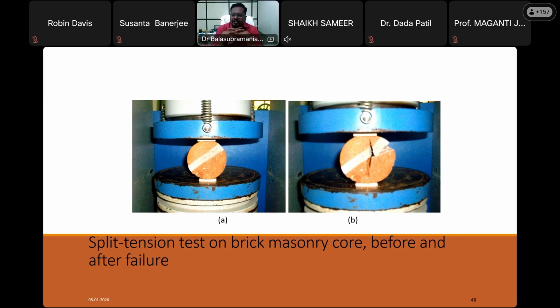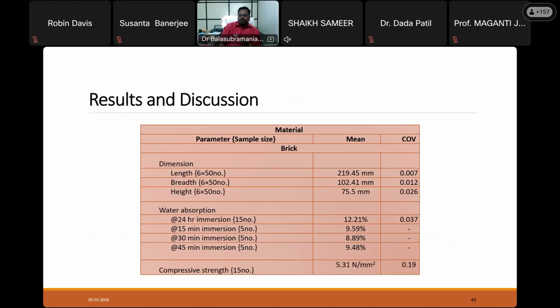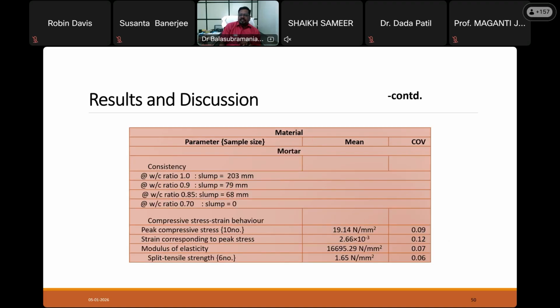Based on that, we can obtain the split tensile strength for the 45-degree angle. Beyond that, if there is any requirement for a different angle, we have to theoretically compare. This can be obtained later based on homogenization techniques, and then we can correlate the angle sensitivity later using expressions. But for the time being, we need some standard values, right? So this is what we proposed. And then these are all the results of those tests.